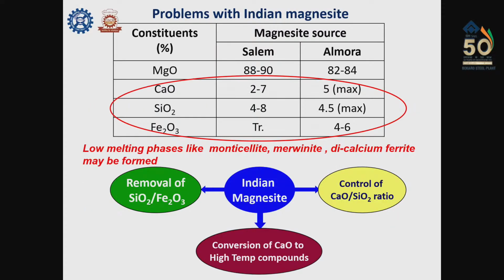So now we see the Indian magnesite. We consider two predominant sources, one is Salem and another is Almora. In Salem, you can see CaO and SiO2 are the major impurities. As such, CaO is not detrimental because it will not form a low melting phase with magnesia. But when it is with silica, it will form low melting phases. In the case of Almora, it contains Fe2O3 also along with CaO and SiO2. That Fe2O3 again can form dicalcium ferrite phase.